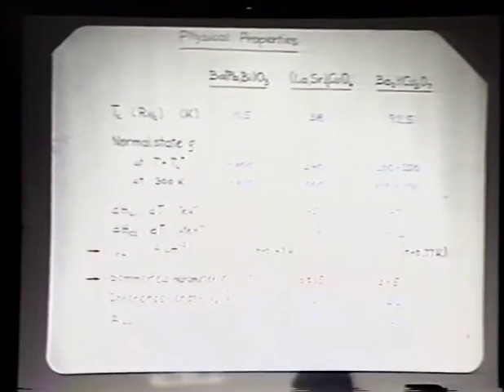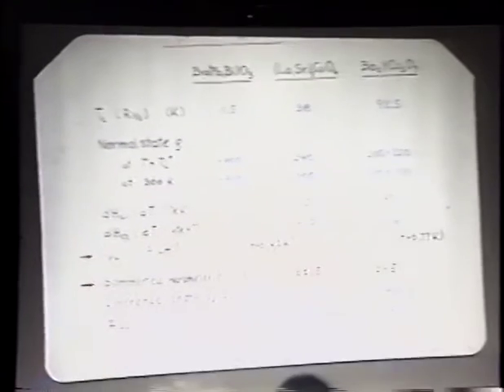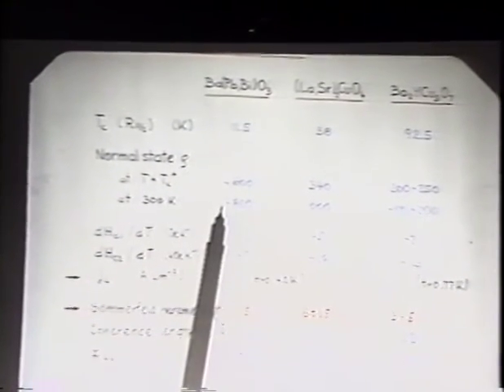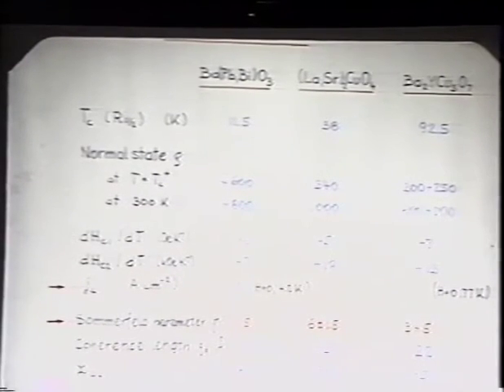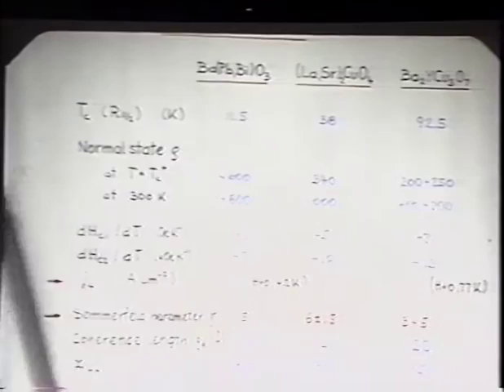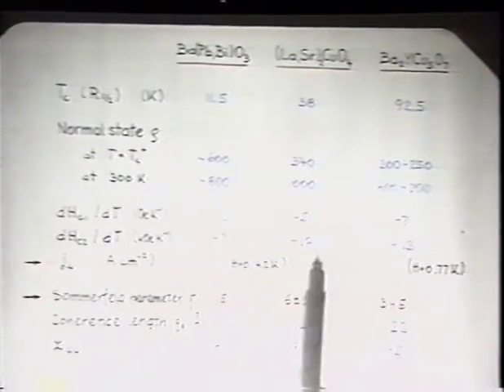But I'd like to compare the three compounds here, barium bismuth oxide, lanthanum strontium, and the barium yttrium copper, with each other. These are the TCs. Of course, we measured HC1 magnetically, and HC2 as a function in resistive measurement up to very high fields at the magnet lab. We measured up to 30 Tesla resistively. These are the values here, typically about 1 to 2 Tesla per degree, a slope for the upper critical field.